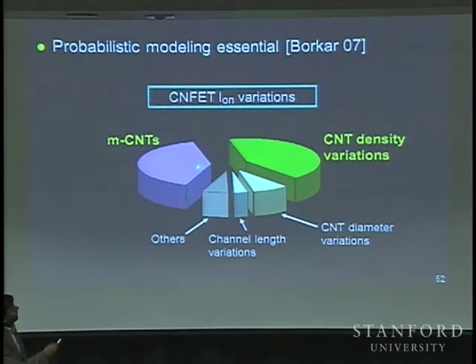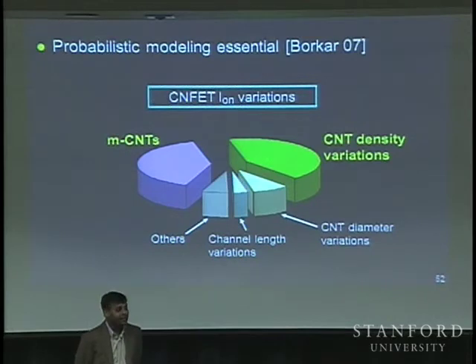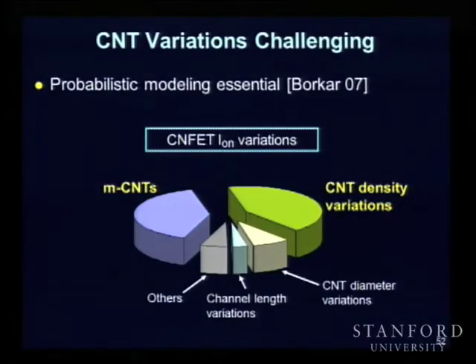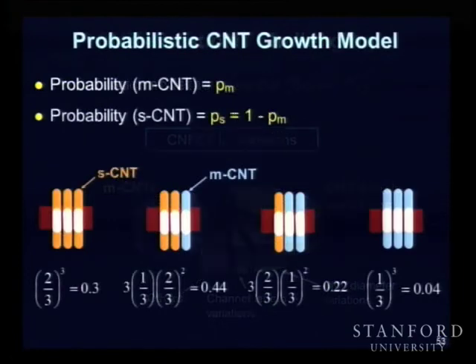And even the metallic carbon nanotubes, I removed the metallic carbon nanotubes after growth, right? What essentially that translates into is variations in the density of the carbon nanotubes, because now I have some useless carbon nanotubes that are sitting over there and not contributing to my currents. So as a result, probabilistic modeling is going to be extremely important if you build circuits and systems out of these carbon nanotubes. Let me show you some cartoons.